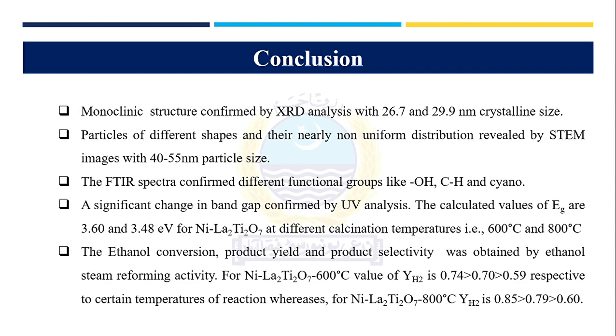The ethanol conversion, the end product yield, and the product selectivity were observed by the ethanol steam reforming activity. The catalyst that was calcinated at 600 degrees Celsius gave the lowest yield of hydrogen compared to the catalyst calcinated at the higher temperature, and the conversion of the ethanol was also observed in this respect. So this is all about my presentation.